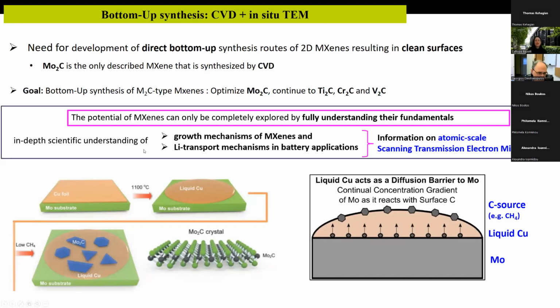So here you can see a schematic of the process followed by CVD, and this is what we want to follow in TEM. If we want to grow molybdenum carbide, practically we need to have a bimetallic layer, a molybdenum substrate covered by copper foil. Then we need to heat it up so the copper becomes liquid, and it acts as a catalyst for molybdenum to diffuse. When it reaches the surface, we need the carbon source, which is methane in our case. So molybdenum at the surface will react with carbon, and finally we will have the formation of 2D nano-sized flakes of molybdenum carbide.